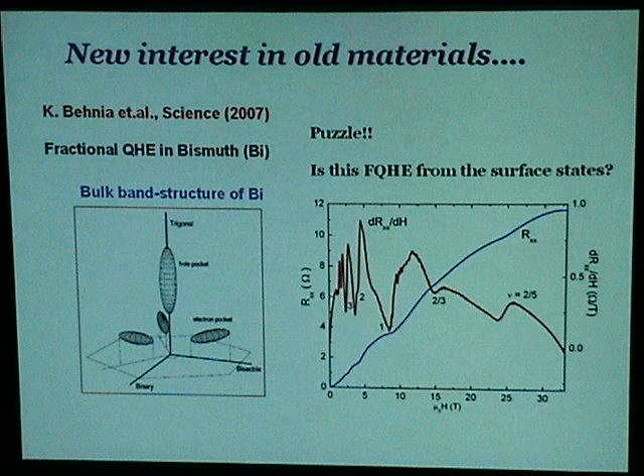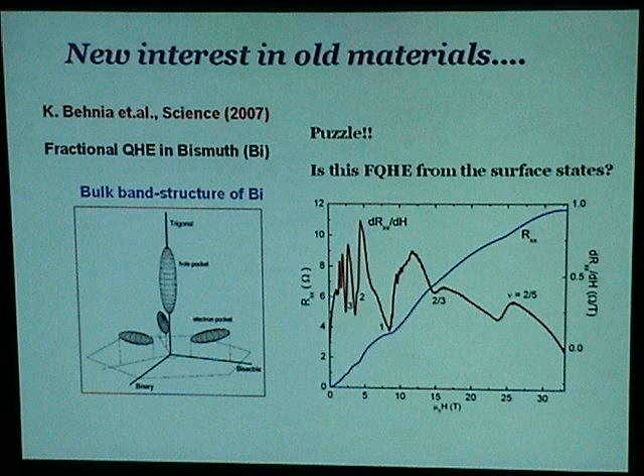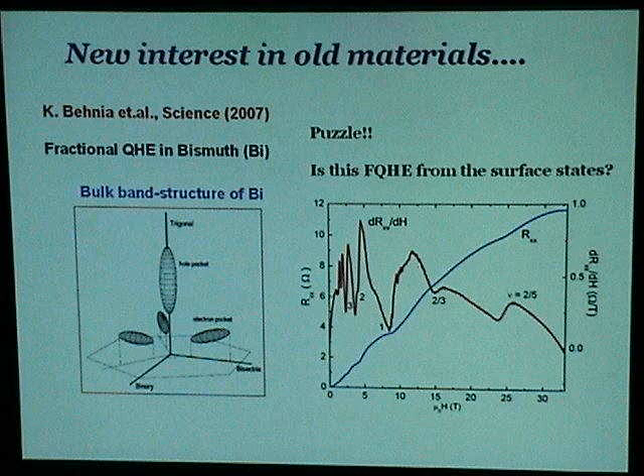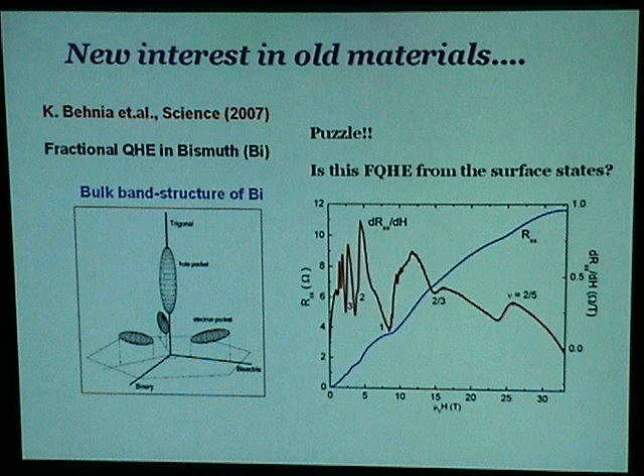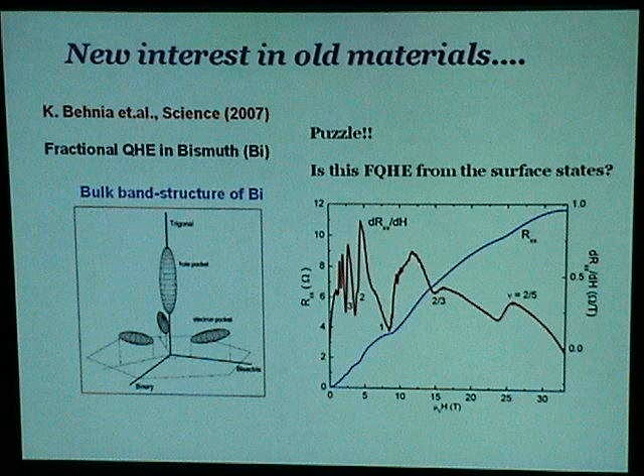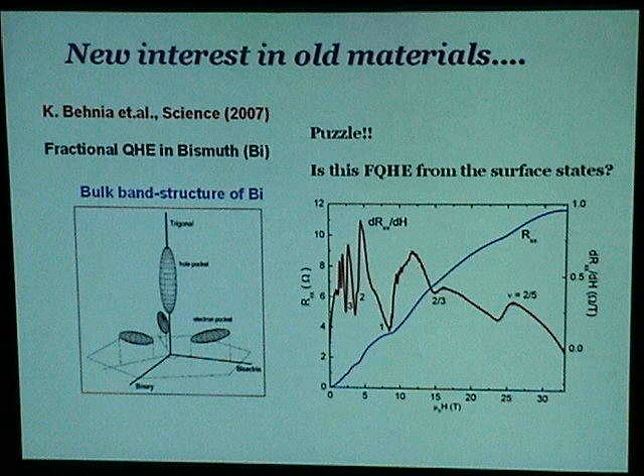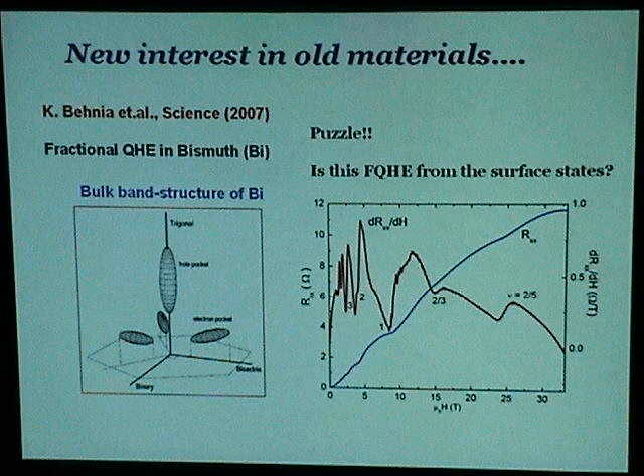So motivated by this, I worried, is this finding related to some hidden surface state in bismuth, which leads to this fractional quantum Hall effect? If you look at the bulk band structure of bismuth, it's very much three-dimensional. So it's a puzzle. The question I pose is, is it related to surface states? And that's something I can measure with ARPES.